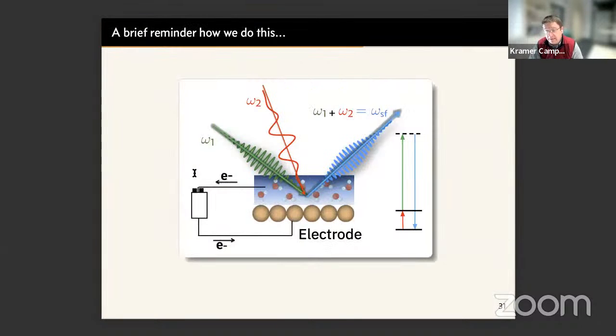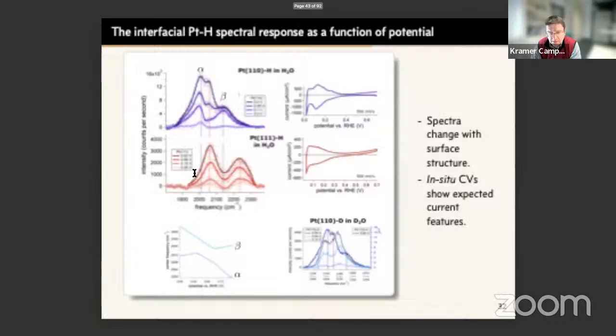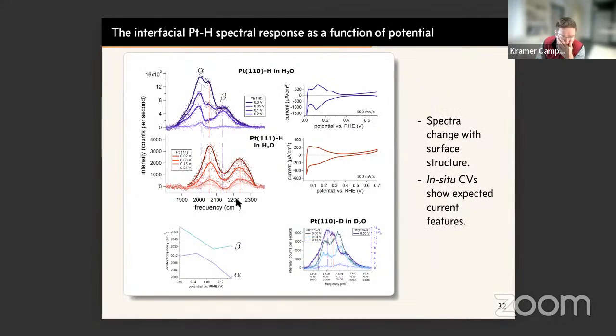So the first thing that we tried to do then is demonstrate that we could probe this, and we also did a vibrational spectroscopy here. Once again, the idea is to do a vibrationally resonant sum frequency probe, in this case looking for the platinum hydrogen vibration of a top adsorbed hydrogen. Some data from this type of measurement are shown here. The x-axis is, as in the case of water, the IR frequency in wave numbers of the incident IR pulse. This is broadband and covers nominally between 1900 and about 2300 wave numbers. It is this range where we expect, based mostly on prior work in UHV and some prior electrochemical work, to find this top adsorbed hydrogen.